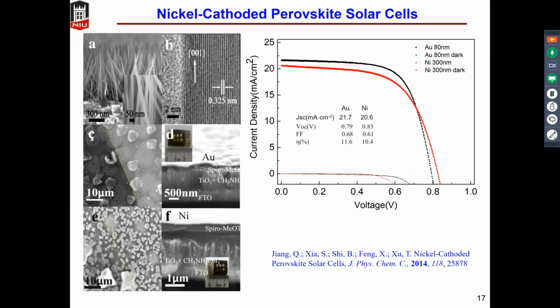And here is the performance of our nickel-based perovskite solar cells, which we published in 2014. At that time, the champion cell was around 14% when we got this work published, and quickly the efficiency record was broken by the Yang group. So we use a different anode material, which is titanium oxide nanowires, single crystal nanowires.